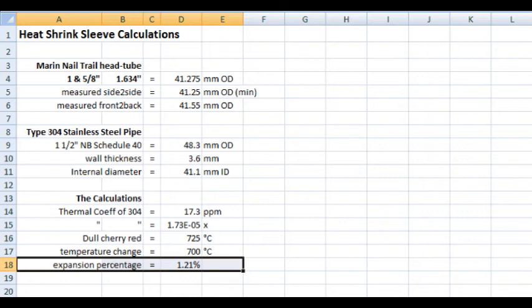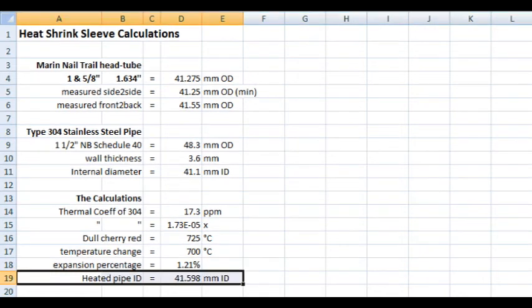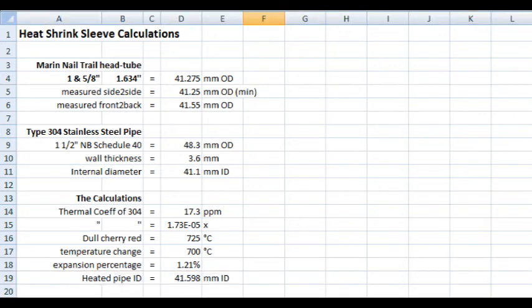So we take our cold internal dimension of 41.1 and increase it by 1.21%, and we get 41.6 millimeters, which is just going to be big enough to slide over the broken, cracked head tube, because its maximum diameter was 41.55. So this will slide on when we've heated it up, and it will cool down and try to be smaller than the smallest dimension of the head tube, and therefore it will be stuck there forever. You'll never get rid of it. It'll just be like a limpet seized on there.